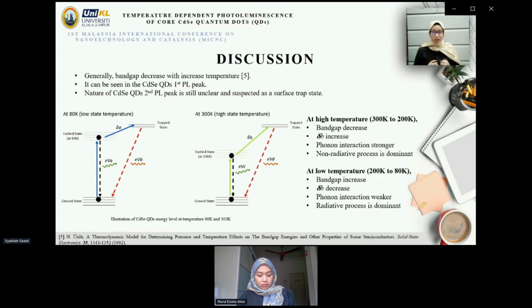In the illustration, we suspected that the phonon interaction plays an important role in transferring electrons from the excited state of quantum dots to the trapped state. At high temperature, delta B shows a much wider gap between the quantum dots' excited state and the trapped state. However, at this temperature region, high phonon interaction will contribute to the non-radiative emission process, which leads to a high intensity in the second peak compared to the first peak, as shown in the figure of PL intensity versus temperature before.